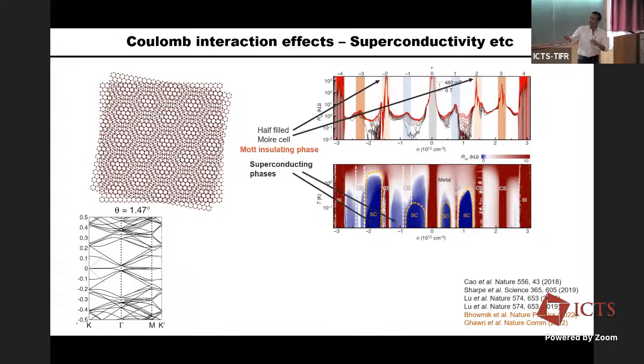And right next to Mott insulating phases, there had been discovery of superconductivity, and there is a huge debate where the superconductivity comes from, whether it's electron phonon induced superconductivity or whether it is superconductivity driven by the Coulomb interaction. Recently, we have looked at these kind of directions as well, and we find that there is a very strong non-Fermi liquid behavior and the strange metallic behavior in this region where the superconductivity has been observed.